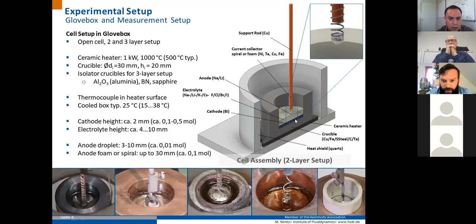The lower electrode, typically bismuth in our experiments, is then filled in the crucible. On top of the bismuth is the electrolyte, here displayed in this light yellow-gray color, and then we lower the other electrode, which is typically contained either in a nickel spiral or a nickel foam, as displayed here, or a similar setup which holds the lithium by cohesive forces, and this allows us to operate the whole system without an electrical insulation outside or in the inside diameter of the crucible.